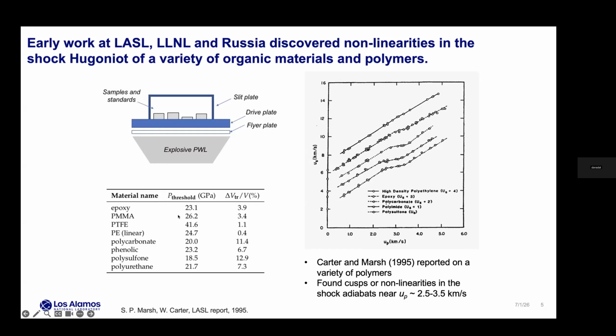Later, colleagues of mine here at Los Alamos published a report based on Bill Carter and Stan Marsh's work in 1995 that basically described the threshold for these cusps in these different polymers and what the volume change across the cusp was. And those cusps were attributed to dissociation of the polymer or decomposition into small molecule products.